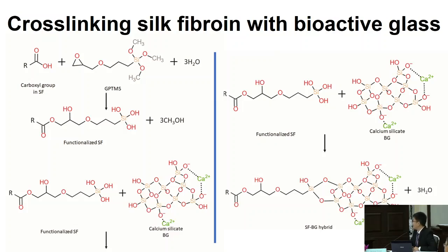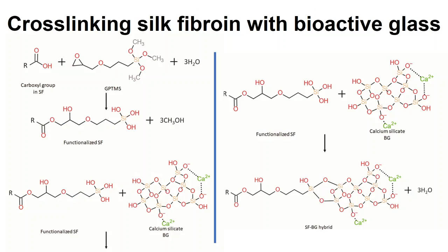So we played a little bit with the chemistry of silk fibroin and bioactive glass. We used a chemical cross-linker called GPTMS. It is an organosilane. It has a reactive group here that can react with the carboxyl group in silk fibroin. So this reaction would functionalize the silk fibroin. And on the other end, in the presence of acid, we can have hydrolysis of this SiO methyl group. And finally, we get SiOH on this side.